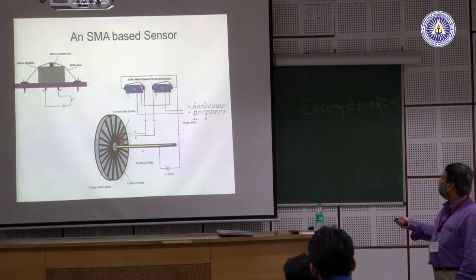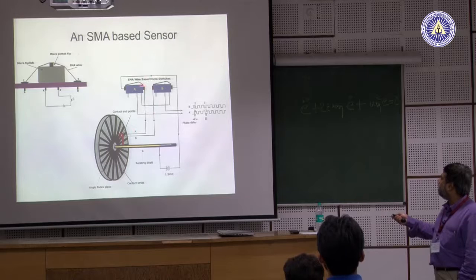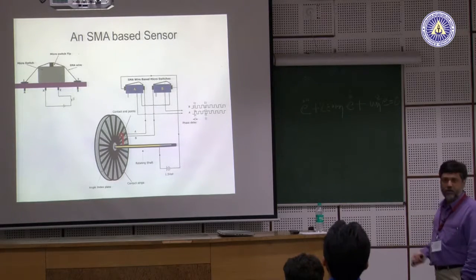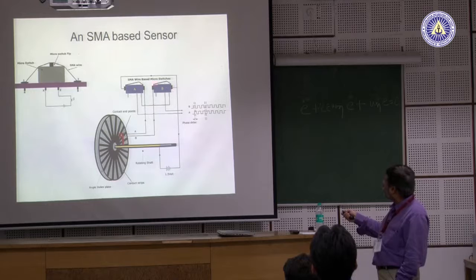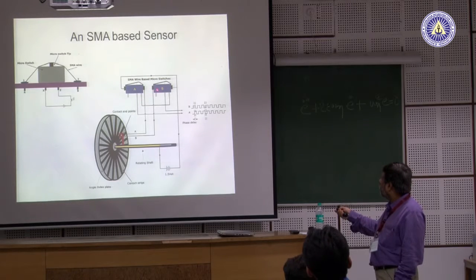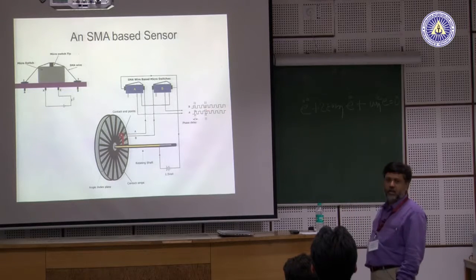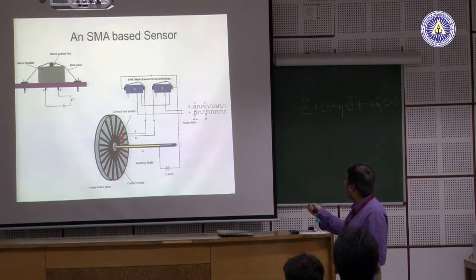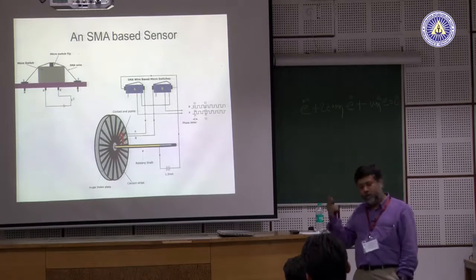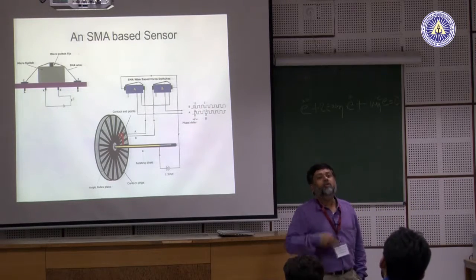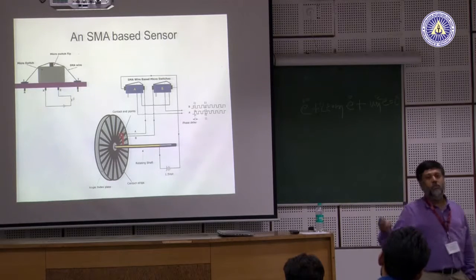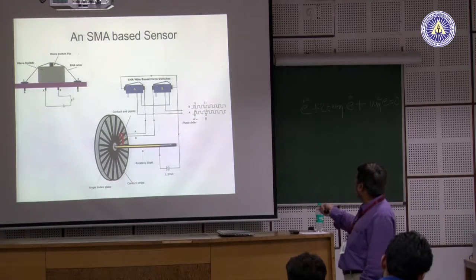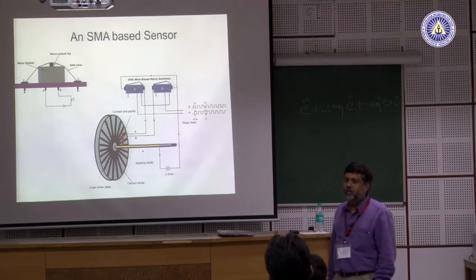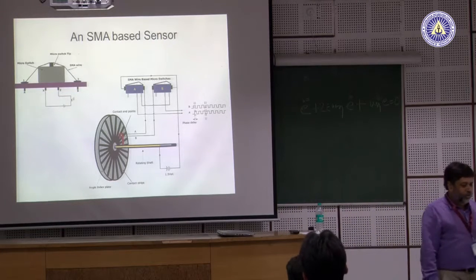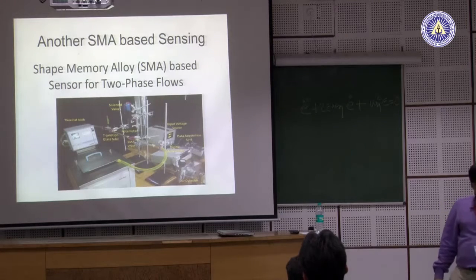Whenever this rotation is happening, it is going from a conductive to a non-conductive layer, and as it is going, current will be passed to A or B depending on whether it is a conductive layer or a non-conductive layer, and as the current is passed, there are 2 micro switches which are sequentially switched on and switched off, and as a result you will get this signal. By taking the difference between the 2 signals, you know what is the angle you have rotated, what is the rotational velocity, acceleration, everything you can get through these 2 micro switch operations. So, that is how you can use SMA as a sensor also.